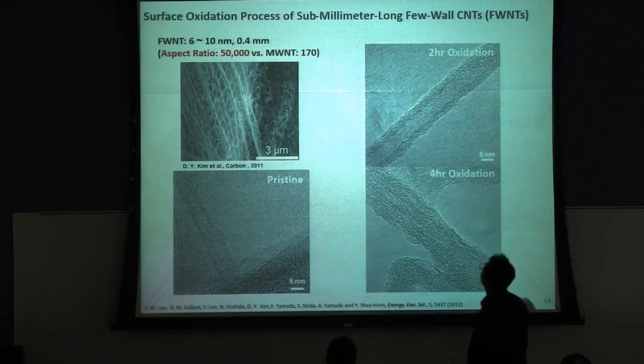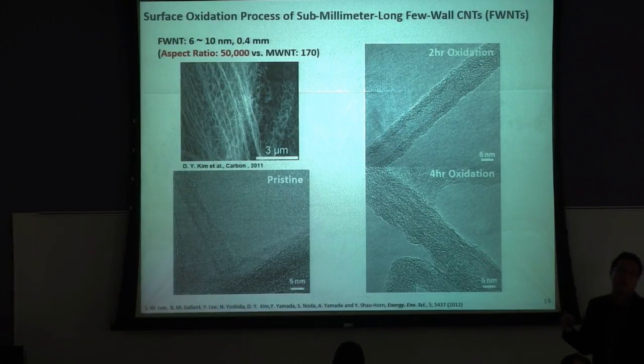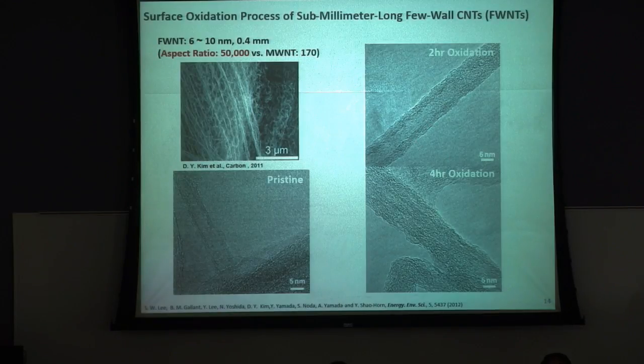After the oxidation process, you can see the surface of this carbon nanotube becomes roughened. Can you guess why? Any guess? Basically, to incorporate the oxygen functional group, oxygen radicals attack the carbon nanotube surface, right? The sp2 conjugation network is now broken. By incorporating oxygen functional groups, sp2 conjugated carbon is converted to sp3 carbon. So we are breaking the surface of the carbon nanotubes as we incorporate the oxygen functional groups.